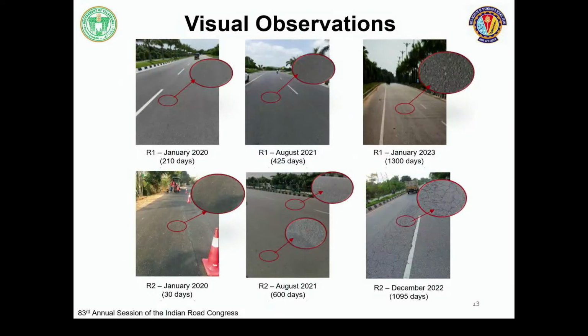Yeah, visually, if you see, the road was good. Generally, we observe something called raveling. We don't worry much. But I was hearing one of the lectures from my colleague's friend from Federal Highway. He was telling raveling was a failure. They consider this as one of the failures. But here we ignore it many a times. We see white patches along the wheel path and we ignore it. But actually, that is one of the major reasons for moisture damage. That is what we observed in this study. I will take you through this presentation to show you that.